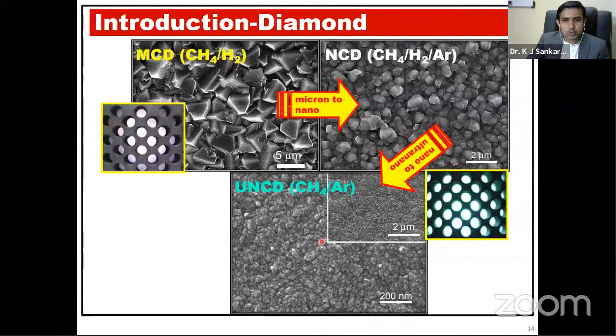So C2 helps to grow this UNCD. Ultra nanocrystalline diamond films have grain sizes of less than 10 nanometers compared with the microcrystalline diamond. These UNCD films are very, very smooth in nature, whereas you can see the microcrystalline diamond as very big rocks of 5 micrometers, so the roughness is really huge. So depending on the applications, we can use different morphologies of diamond.